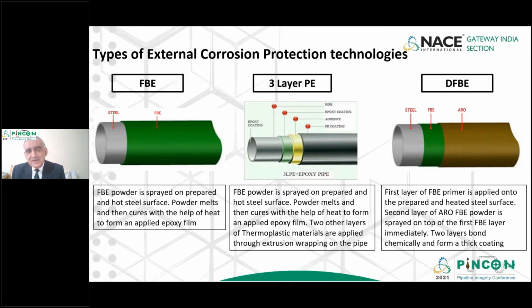Then the third picture you see on the right side is a new technology. It's called dual layer FBE coating. And why is dual layer FBE coating used? This technology has been introduced in the last 20 years. The first layer is still FBE and the outer layer is an abrasion resistant overcoat FBE. This is also fusion bond epoxy material with very high impact resistance, very high hardness, and good weathering properties. And the beauty is that these two materials react with each other and make a structural bond. So after the coating is applied, it becomes a unitized dual layer coating.